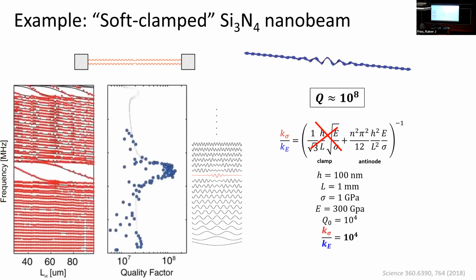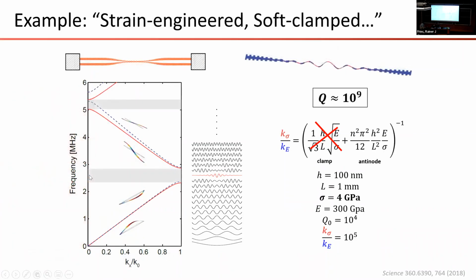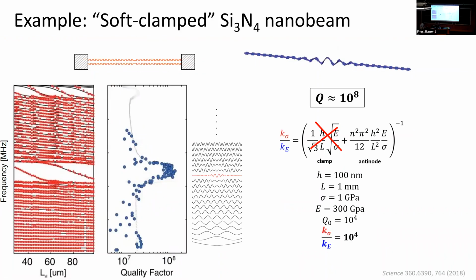So it's just some data here. The fun thing is that if you're really careful and you study the vibrational modes of these structures, you get sort of standard dissipation dilution, and suddenly when you hit the band gap and start studying these localized modes, they can have much higher Q just due to soft clamping. This is not one beam, by the way. This is us measuring 25 different beams and then compiling all the different quality factors. This is a tough measurement.